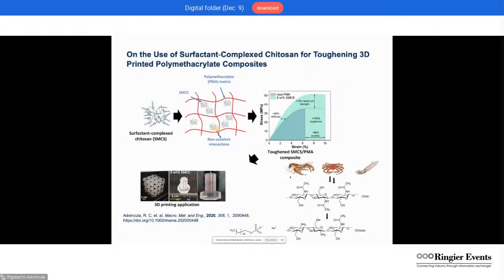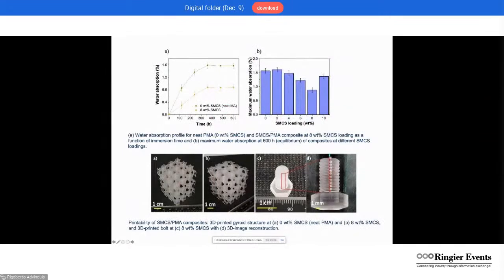So in this case, the chitosan derivative is complexed with the surfactant and mixed with the resin, and then we can 3D print them, shown in these objects, with improvement in the tensile strength values, toughening as shown here compared to a native resin, with as much as 8% addition of the complex chitosan. And here are the prints, a gyroid structure and a bolt, produced again by SLA, so we can get very high resolution in their swelling behavior.